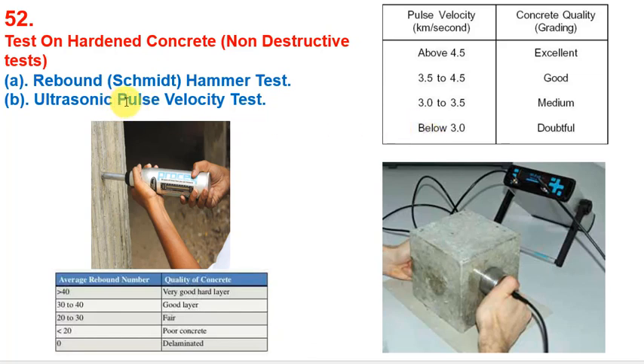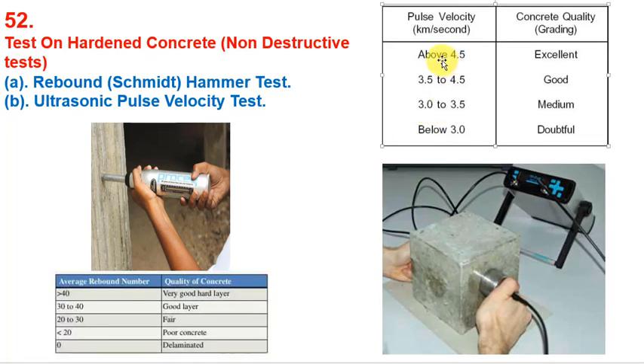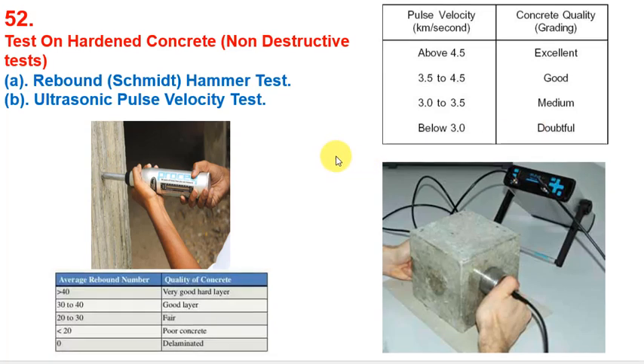And the second method, ultrasonic pulse velocity method, this is the device you can see in the image, in which we use pulse velocity to find out the concrete quality or grading of the concrete. And this table is showing the values. If the value of the pulse velocity is above 4.5, then the grading of concrete or quality of concrete is excellent. If it is between 3.5 to 4.5, then that is good. If it is between 3 to 3.5, its quality is medium. And if the pulse velocity is below 3, then that concrete quality is doubtful. Got it? So the important point is that these are non-destructive tests.